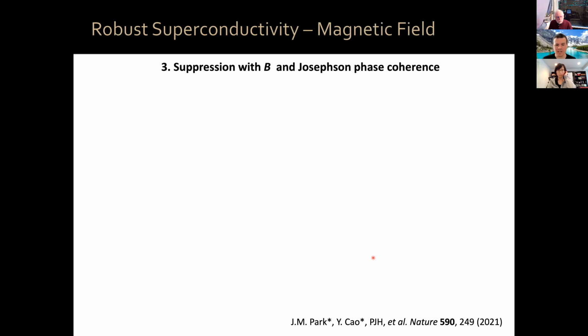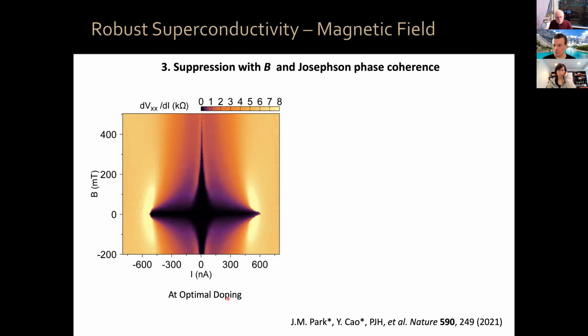So if you are near optimal doping, where the superconductivity is very strong and uniform in your entire sample, you apply a perpendicular magnetic field, you kill initially superconductivity on a fast scale of order 100 millitesla, with then a long tail up to about half a Tesla.